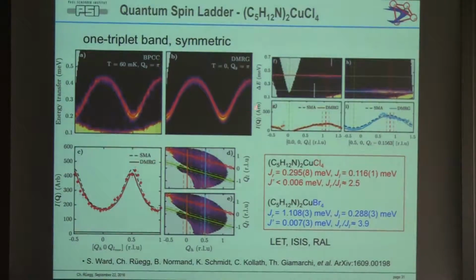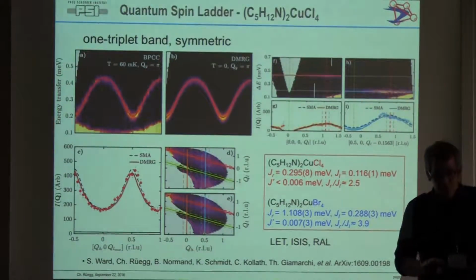We fit this with a theory, and you extract exchange parameters. Now everything we do from now on is basically based on exchange parameters which are fixed by this determination. So you can basically then calculate with DMRG the mode, including the intensities, the matrix elements, and you see very good agreement. Now the beautiful thing about the spin ladder is actually there's an extra symmetry.